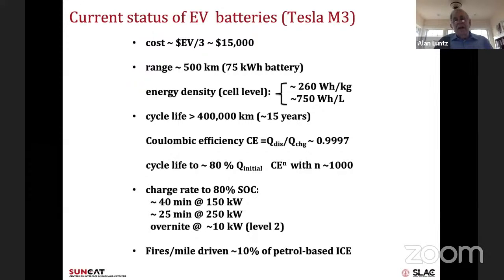So the cycle life is something like 400,000 kilometers, or about 15 years of normal driving. And that's principally determined by the Coulombic efficiency of the battery. When you discharge and charge a battery once, you lose a little bit of the active lithium. And the fraction that you retain is given as the Coulombic efficiency. So if you want to charge and discharge, say 1,000 times, and still maintain about 80% of your battery capacity, which will give you this kind of a lifetime, then you need a number something like this in the Coulombic efficiency. So this is a very important number for the lifetime of the battery.